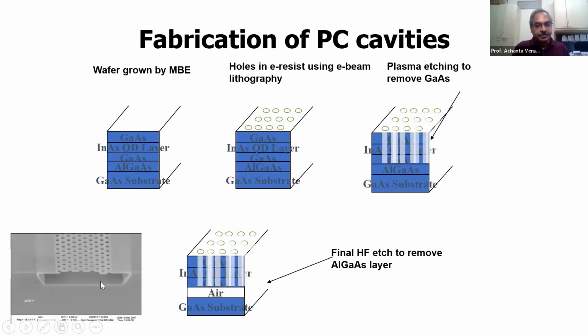So you have air below and air on top, and you have this very thin, 100 to 150 nanometer thick periodic hole arrangement wafer hanging, which has quantum dots inside. People have shown different applications, including single photon emission from these structures. The Q factors are large because of this defect creation, where the holes are not completely periodic. You basically design a point defect within this whole array.